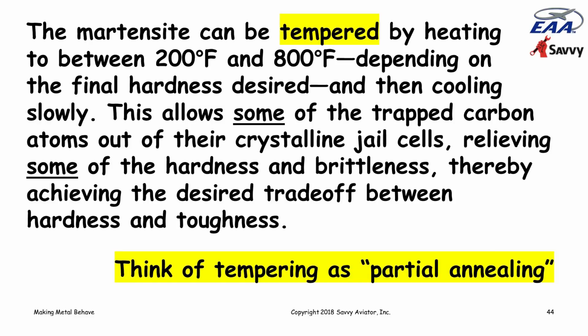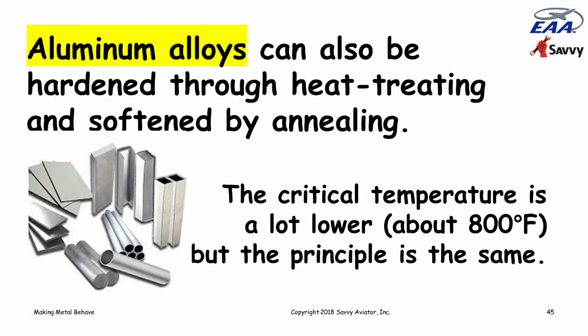Aluminum alloys also can be hardened through heat treating and softened by annealing. I won't go into all of the chemistry of how that works, but it's very similar in principle to how it worked with steel. The critical temperature of aluminum is a lot lower. It's about 800 degrees Fahrenheit, not 1600, not 1400 degrees, but the basic principle of how heat treating and annealing works for aluminum alloys is pretty much the same.